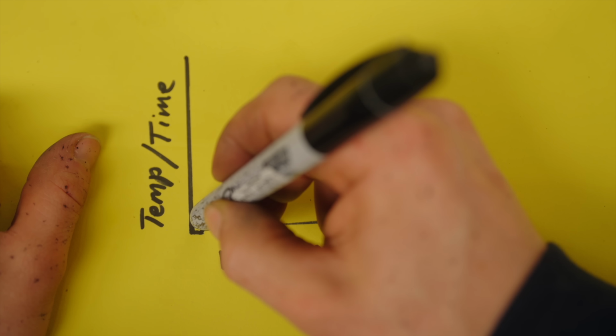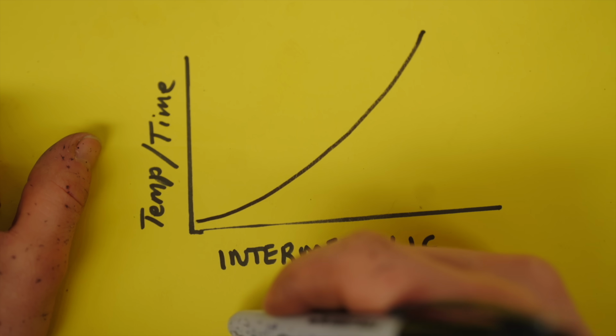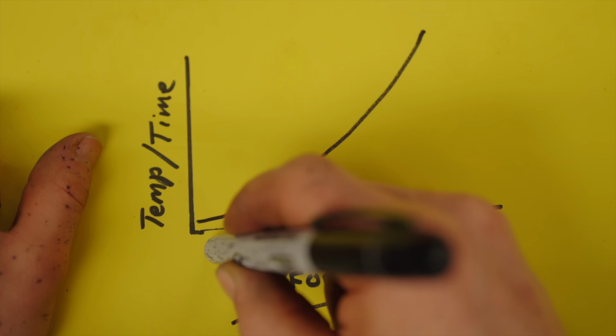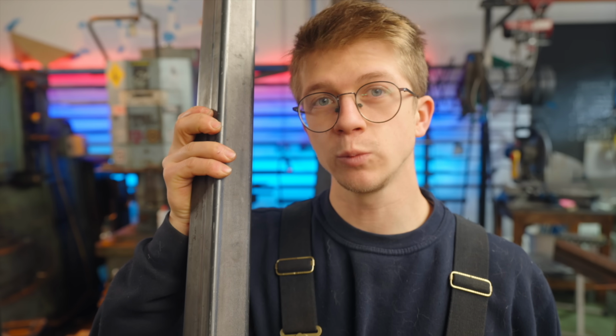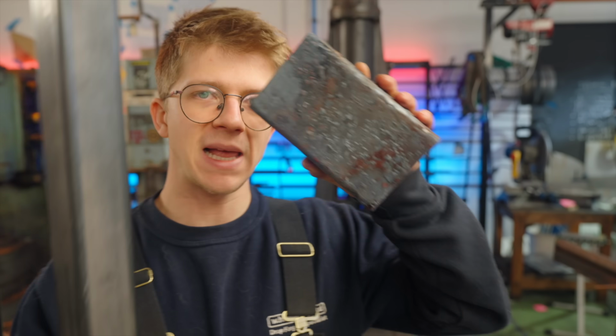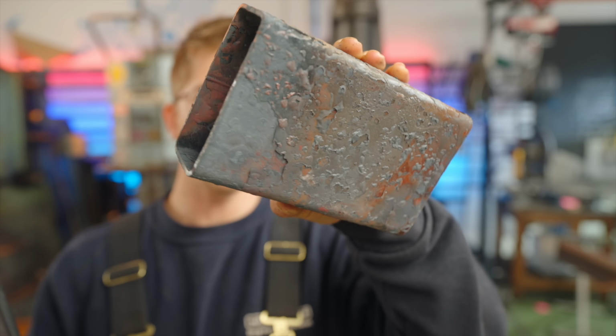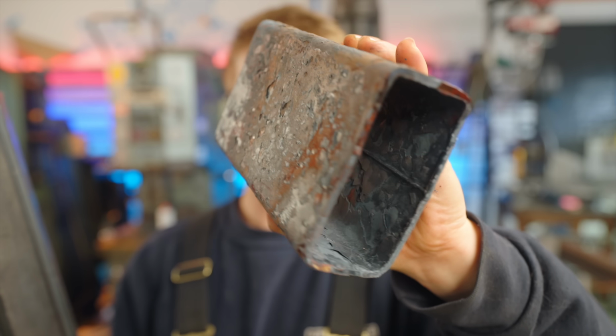But the elephant in the room as it relates to titanium and steel is, of course, the more you increase temperature and time, the more intermetallics are formed. It's just like a high school chemistry experiment. The more temperature, the more excited the atoms, the faster the reaction. It's why this bar of steel will stay looking like this for hundreds of years, but a couple hours at high temperature, the oxygen reacts with the iron like crazy, turning it to iron oxide at an incredible rate.